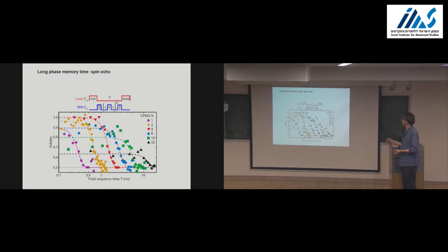And so with a significant number of pi pulses, where it decouples well, you can reach millisecond coherence time at this temperature of a few hundred millikelvin. So lowering the temperature allows you to reach very significant coherence time for this defect, combining now good optical access to individual atoms with long coherence time of the spin state in the ground state.